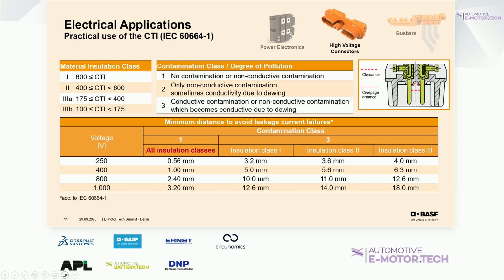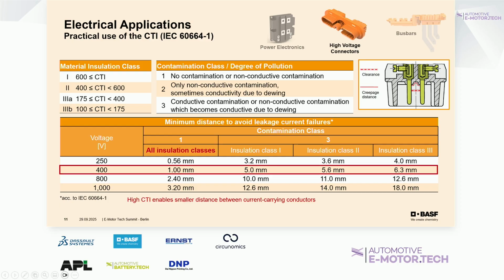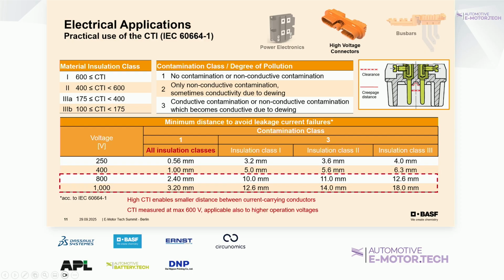So you see here also some examples. Typically it's combined with a material insulation class and also a kind of contamination class of your application. So whether it's sealed or not sealed, you have different classes. But you see here in this table, you are also allowed to use a CTI 600 or 400 material in an application with 1000 volt, but you just need to increase the thickness, the distance of your metal pins. So it's important to mention, you can also use CTI 600 materials for 1000 or 1500 volt applications. This is, I would say, in the industry also commonly in use. So there's nothing untypical here.